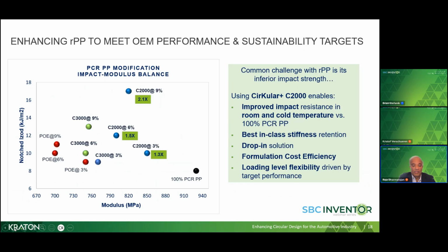As you all know, when you enhance impact, there is also a slight trade-off in modulus, which is shown here in this graph. But when you compare the performance of our Circular Plus products to the POE, we have a much better impact stiffness balance. So we don't lose modulus to a large extent as compared to the POE modifiers, as you can see from this slide.